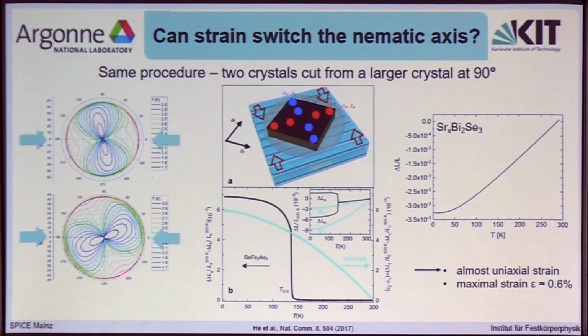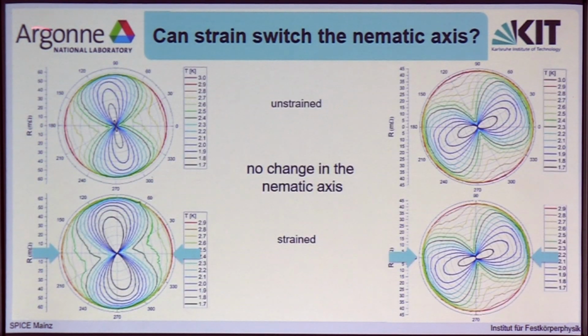So for the 2 samples that we mount next to each other, you see here indicated the direction in which they will be compressed, since they are glued on this glass fiber reinforced plastic. And if our sample were to follow the substrate perfectly, we could expect a maximum strain of about 0.6% due to the mismatch in thermal expansion. Now we've done this experiment, and you can see here we've remeasured these constant temperature field in-plane sweeps, and you can see directly that we observe no change of the nematic axis in both cases.